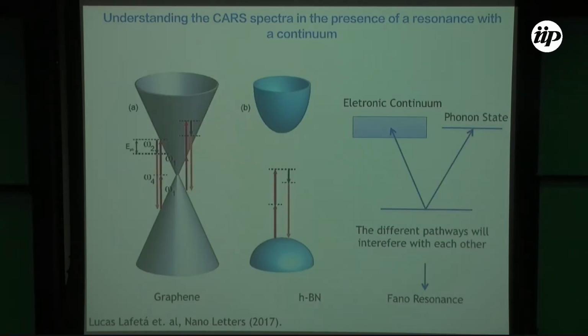So in order to understand this, we need to take a look at the band structure of the two different materials. In graphene, because it's a zero band gap semiconductor, all of these four-wave mixing processes are resonant. So you have the electronic resonance, the resonance of the incoming photons with the electron states, and also the resonance with the phonon states. In the case of boron nitride, because it's a wide band gap semiconductor, an insulator, you don't have the resonant part related to the electronic part. You just have a resonance with the phonon.